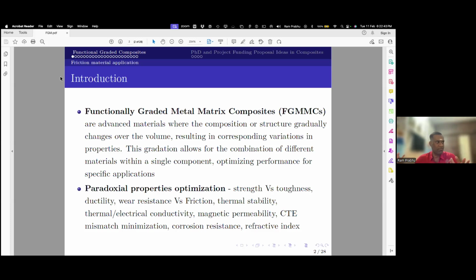Take an example of ceramic, which has very good thermal stability but doesn't have conductivity at all. The same applies to electrical conductivity, magnetic permeability, and coefficient of thermal expansion. When I put two different ingredients into the material which have a wide difference in CTE, it introduces thermal stress in the material, leading to cracking or other kinds of problems.